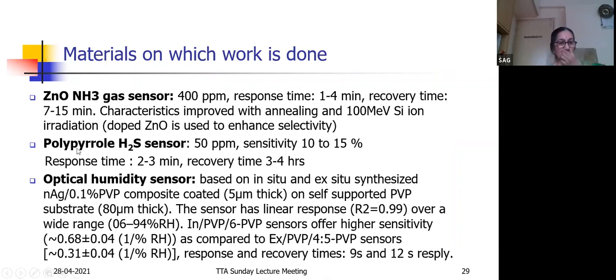Then we worked on a polypyrrole sensor for H2S gas. At 50 ppm, the sensitivity was 10 to 15%. Sensitivity can be defined in different ways, maybe in percent sensitivity or in terms of change in resistance. Response time was 2 to 3 minutes and recovery time was 3 to 4 hours.